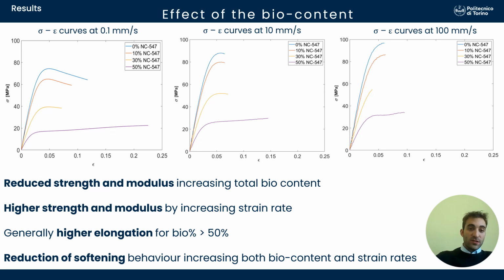Here are reported the stress-strain curves coming from the tensile test for the 4 different resin blends, considering the 3 different strain rate values and with the objective to highlight the effect of the total bio content. In fact, by increasing the total bio content, we can see reduced strength and modulus, whereas by increasing the strain rate, the strength and modulus are higher.